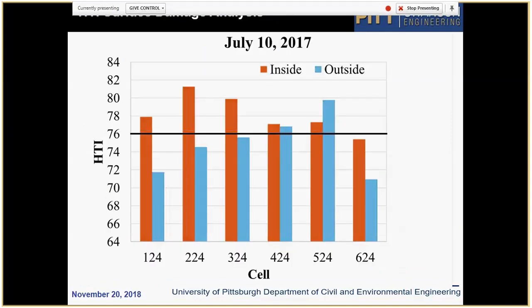So higher area means greater damage in concrete, because it means that the signal is more distorted. In this case, we found that control cell 624 does have slightly lower damage, but the damage for all cells was not very high. Maybe there's an exception inside lane for 224, but even that one, we're not sure how confident we are.